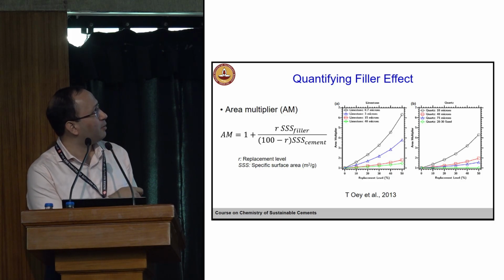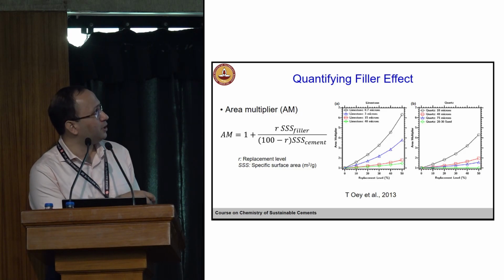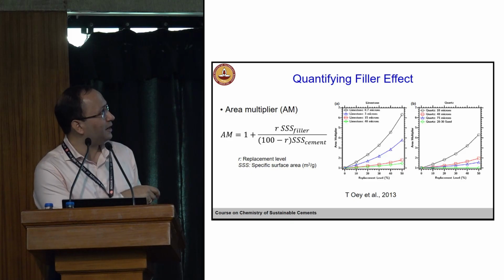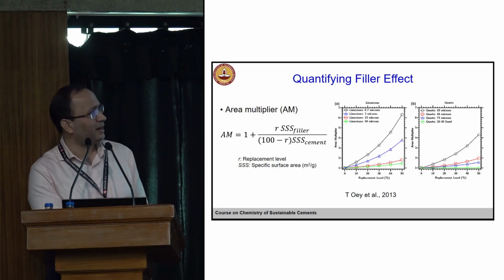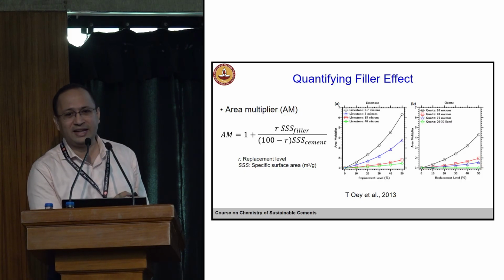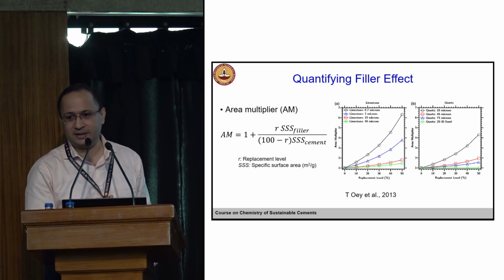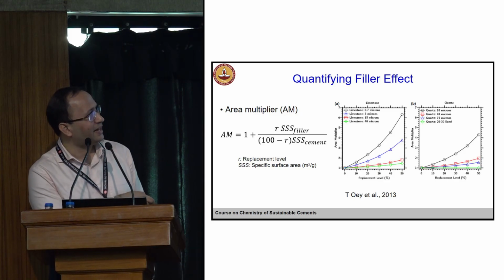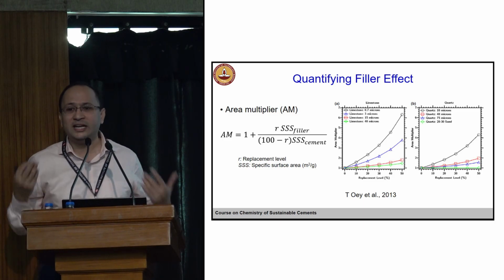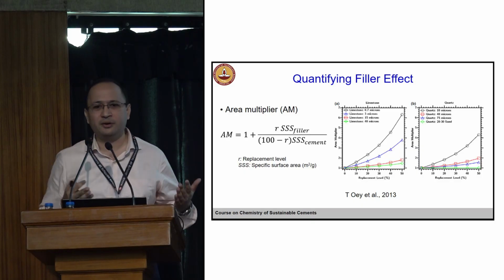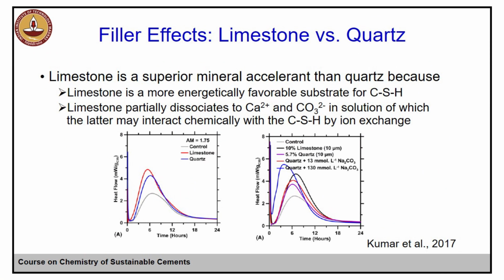So again, for this filler effect, they came up with this area multiplier, which is proportional to the specific surface area of the filler and its replacement level. You can come up with this area multiplier, and perhaps that can be used to compare different sizes of the same material, limestone. What will that change? It will change the specific surface area. That's the number which is going to change. So it tells us the 0.7 size has a higher area multiplier, and how that will affect the heat of hydration. And this was again used for quartz of different sizes. This could be one way to quantify. When we talk about a filler effect, how do you quantify? How do you compare different sizes? This could perhaps be a good way to do that.